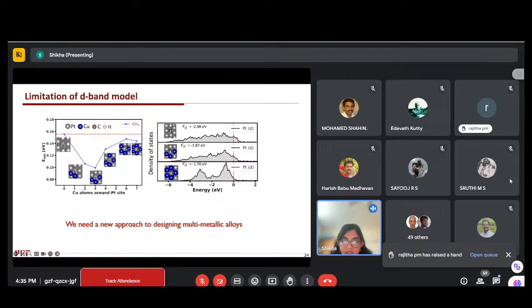So now, one more example, if we see where the D-band model fails. Here we have one example: the adsorption energy of a CH3 molecule on the platinum site. So we have a given adsorption energy. Now we change the surrounding of the platinum site by adding copper. By adding the copper to the platinum site, we shift the D-band center towards the Fermi level. So if we shift the D-band center towards the Fermi level, it should be more reactive. So we should have a linear pattern like this.